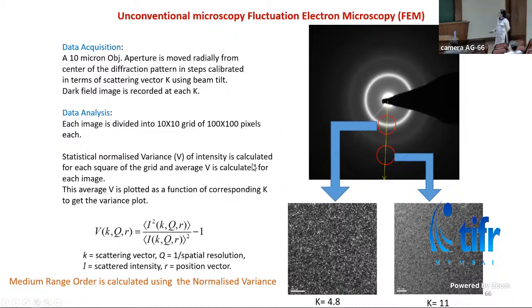Bulk metallic glasses generally have MRO, and the hardness of the BMG, bulk metallic glass, depends on the medium range order present in it. So here is a technique to evaluate the medium range order in the sample. Since the sample is amorphous, we get a diffraction pattern like this. And if we put an objective aperture across the diffraction pattern and move it radially, we can collect